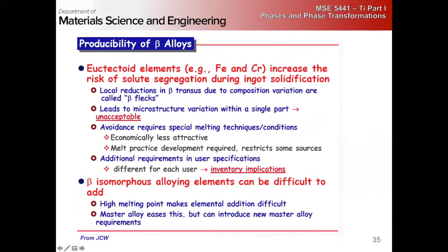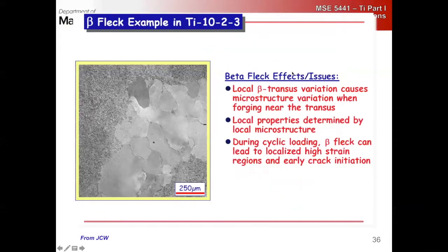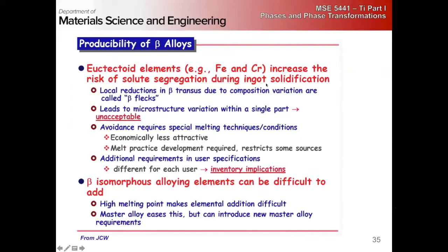The first is that anytime we add eutectoid elements, iron and chromium, we have this issue with solute segregation during solidification, right? And since these elements have a strong effect on the beta transus temperature, if we get segregation, we have an inhomogeneous beta transus, and this leads to a nasty casting defect called beta fleck, right? And this gives us really bad microstructure inhomogeneities in a single part, right? So essentially, to avoid this, there's a whole bunch of different melt practices that are employed. It's not worth going through them, but it makes the cost of processing these alloys quite a bit more, right?